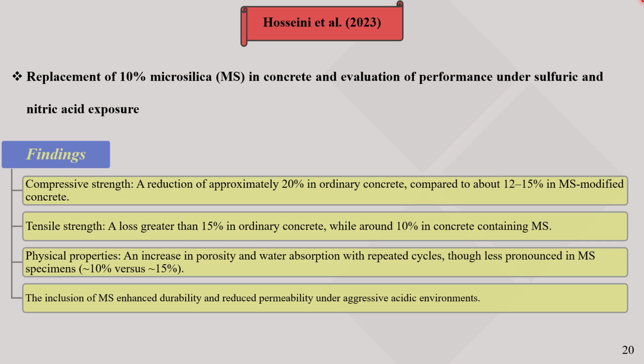The next study was conducted by Mr. Hosseini and colleagues. They replaced 10% of cement with microsilica and evaluated concrete performance in sulfuric and nitric acid. Results indicated that compressive strength in ordinary concrete decreased by 20% under acidic exposure, whereas in microsilica-containing concrete, the reduction was limited to 12 to 15%. Tensile strength decreased by 15% in ordinary concrete but only about 10% in concrete with microsilica. Overall, microsilica enhanced durability and reduced permeability in corrosive environments.